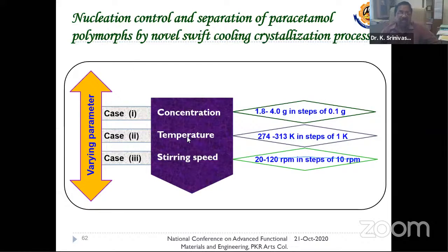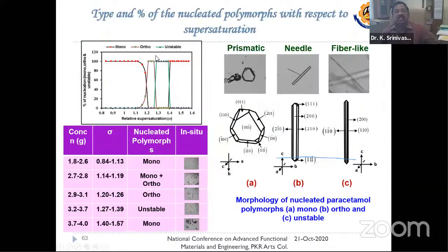and the parameters we took: one is concentration, another one is temperature, another one is stirring of the solution, its velocity. We adjust the concentration in this range and the temperature in this range, and various steps followed for stirring this solution continuously. And we cool down the solution from a high temperature saturated condition to room temperature or below room temperature conditions. And there we were able to create supersaturations at these levels, sigma.